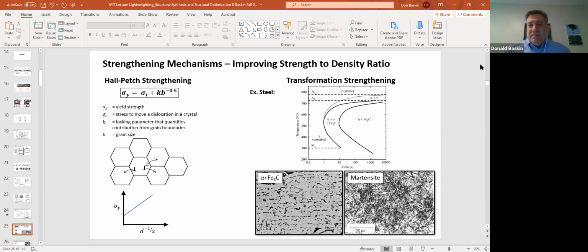Another strengthening mechanism has to do with grain size. It's called Hall-Petch strengthening. What this theory holds is that the yield strength of a material is inversely proportional to the grain size. There's some controversy about exactly why material strengthens as the grains get smaller, but it has to do again with our friend the dislocation. Dislocations, in order to continue to have a material that deforms, need to hop over grain boundaries, the spaces between these atoms, in order to keep yielding.